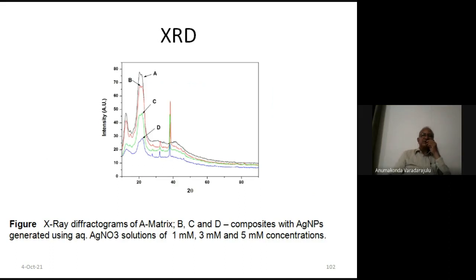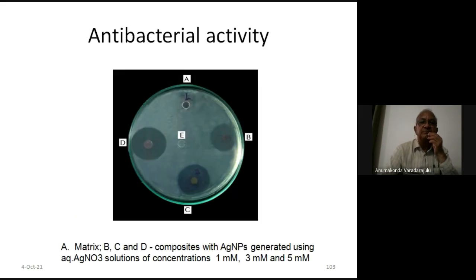And using X-ray also, the matrix did not show any peaks, whereas the nanocomposites showed some additional peaks, which correspond to the metal nanoparticles. So using the SEM, TEM, and then XRD, you can prove the presence of these nanoparticles inside these nanocomposite films and so on.